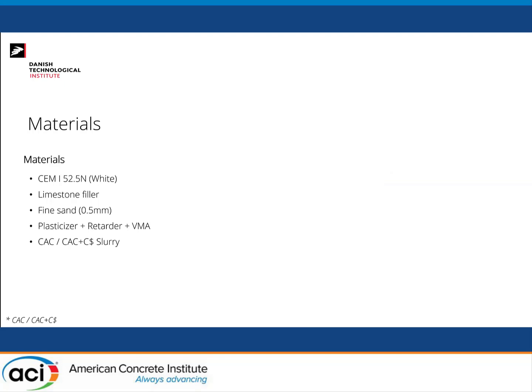So the materials that we used, there is no magic in it. They were all off-the-shelf materials available here in Denmark. Elsewhere, you would find equivalent materials. We're using a standard CEM I, the only detail is that it is a white cement, limestone filler, fine sand, and then a combo of plasticizer, retarder, and viscosity modifying agent. This composes the base mix. And that base mix, which is heavily retarded, is then activated by a slurry composed of calcium aluminate cement and water, or calcium aluminate cement plus calcium sulfate and water, to be injected in the nozzle.